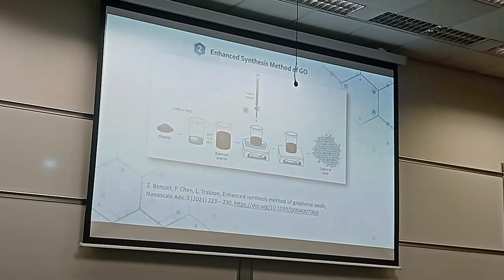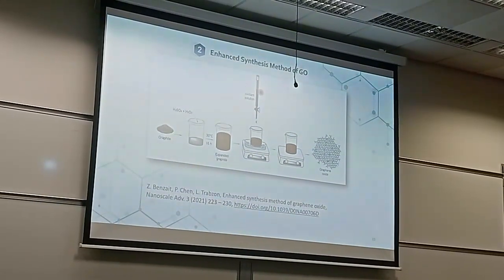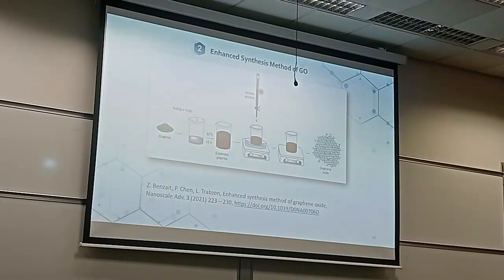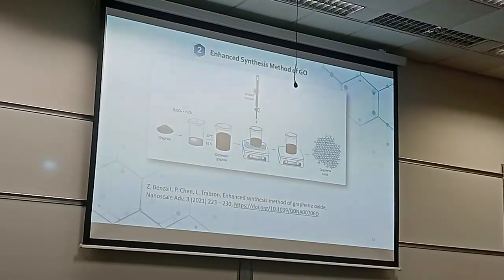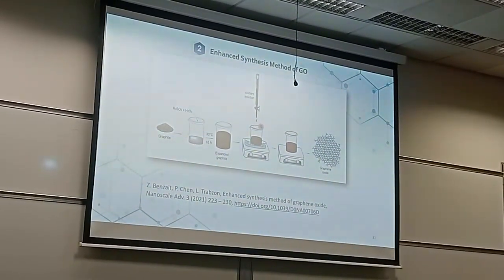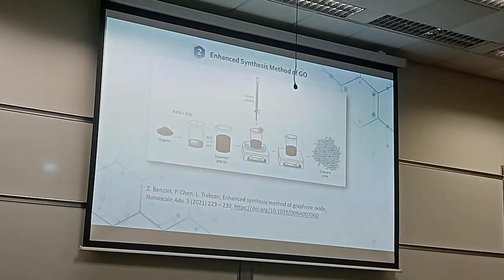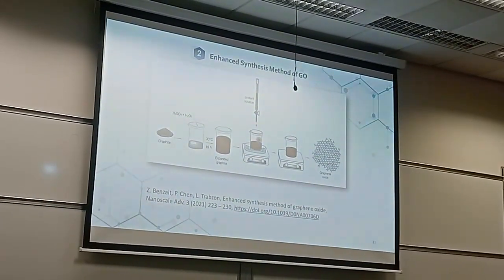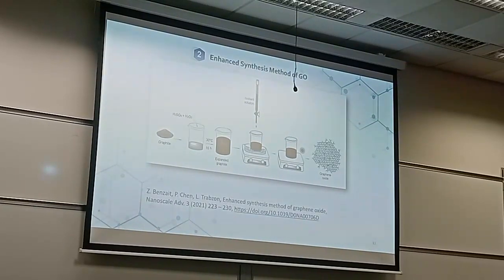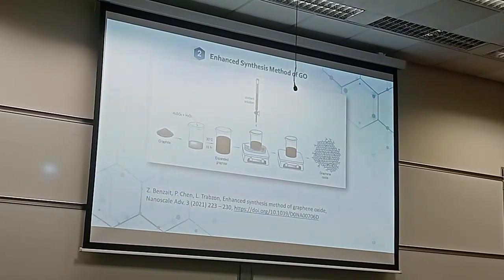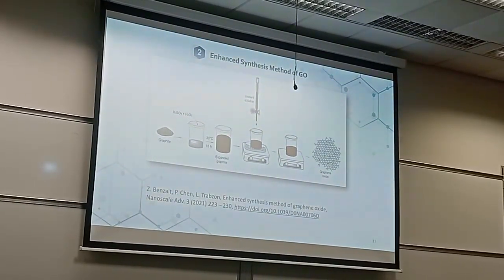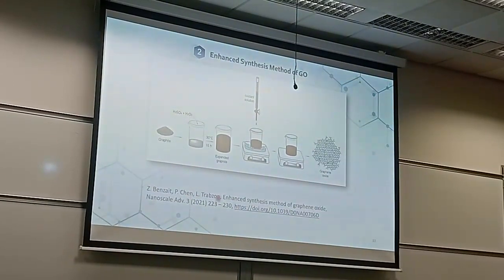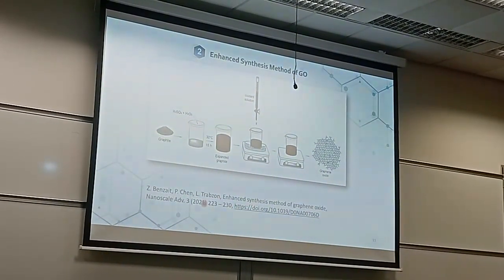We mix the oxidants with the sulfuric acid and phosphoric acid together. Add it slowly while mechanically stirring the mixture, and doing it at low temperature. Then we can raise the temperature after introducing the whole oxidant solution. You can find more details in this article.